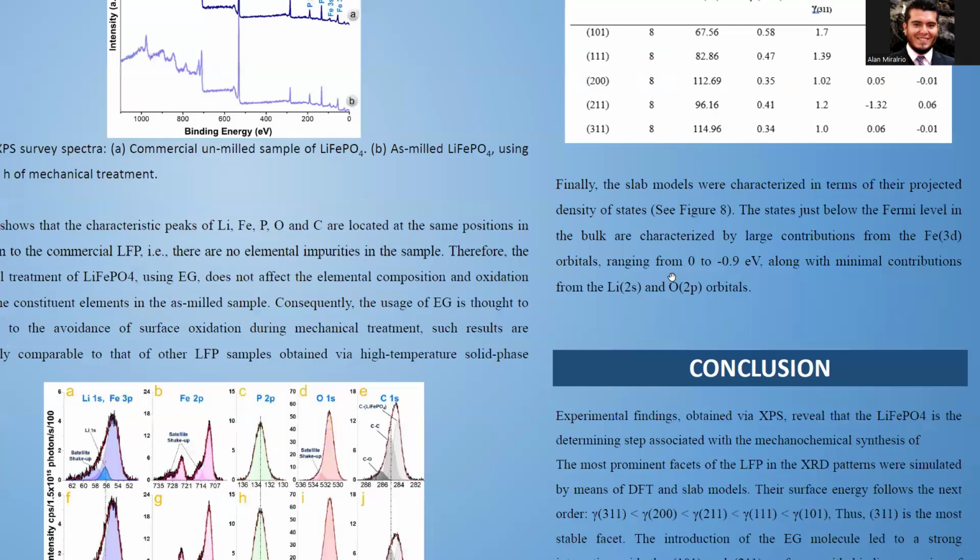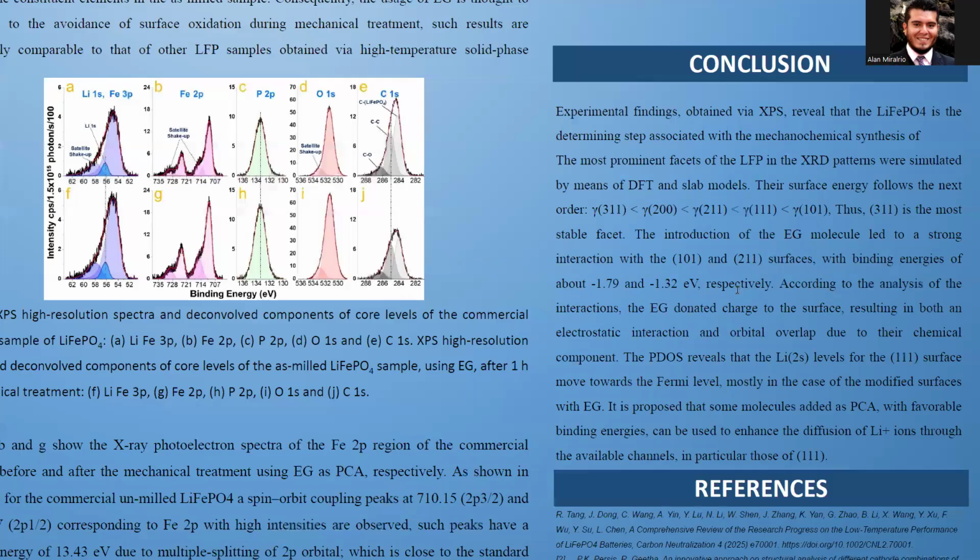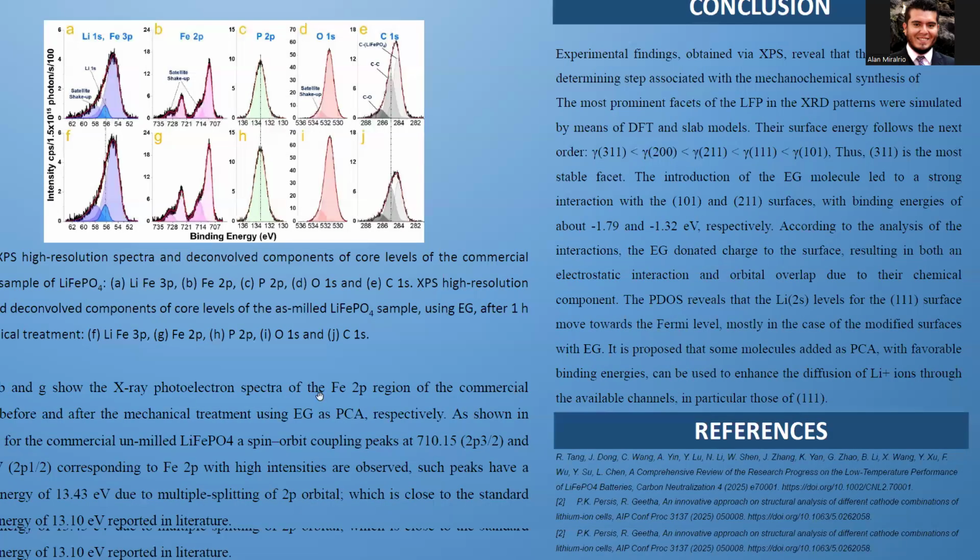Finally, we conclude that the process control agent works well in order to produce favorable binding energies between the ethylene glycol and the LFP surfaces, contributing to enhance the diffusion of lithium ions through the available channels, in particular those of the 111 facet.